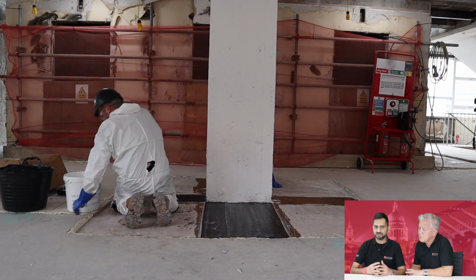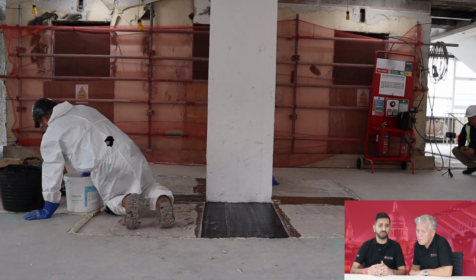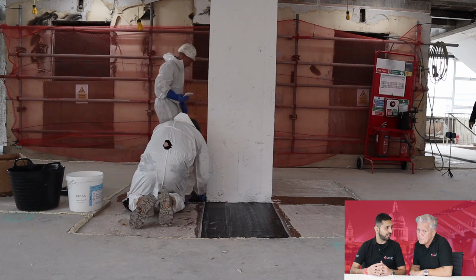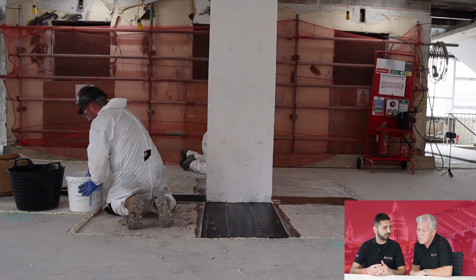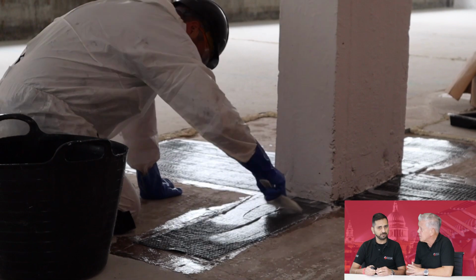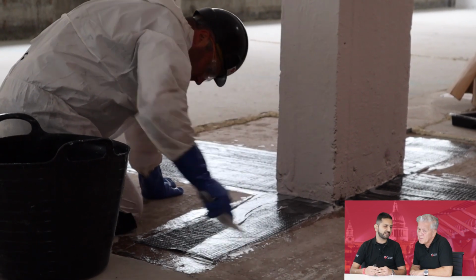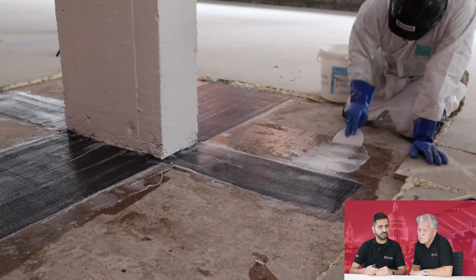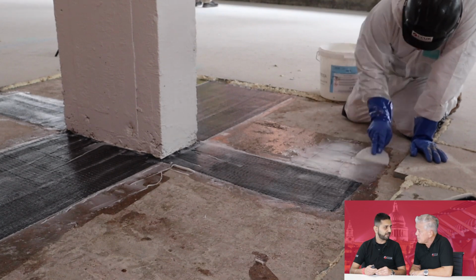And after that, this is the finished section. If you want, you can screed over it, plaster it, paint it, render it. You can do anything on top of it. It will be 100% cured in 72 hours in ambient conditions, so you can reload your structure back to its new capacity in 3 days.